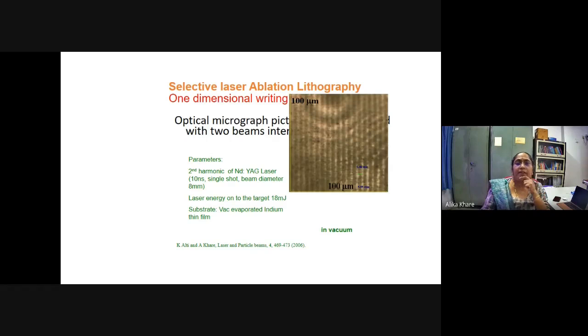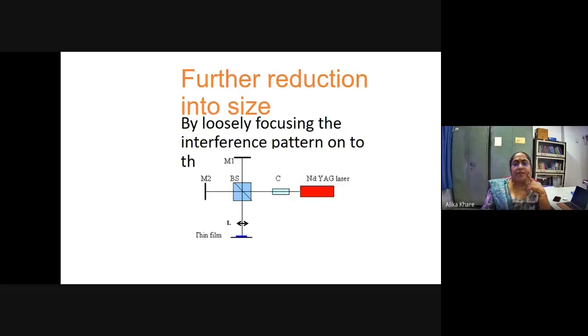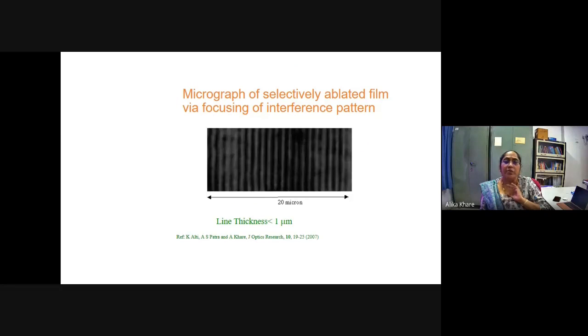Here is one example I would like to share: one is able to write these parallel beams. The scale here is nearly 100 micron, and this was written onto a vacuum-evaporated indium thin film. Here the size is quite large, so what we did was slightly compress the interference pattern and loosely focus it onto the thin film. If we tightly focus it, we get two spots, but we need to have the overlapping region of the two beams. So we loosely focused it onto this, and this is how we could compress it.